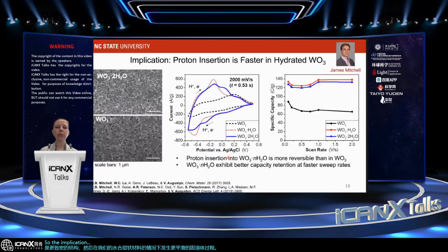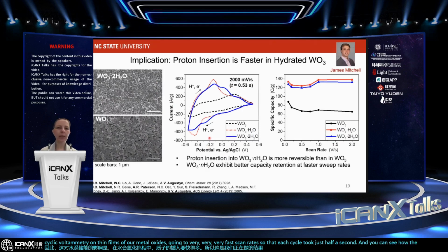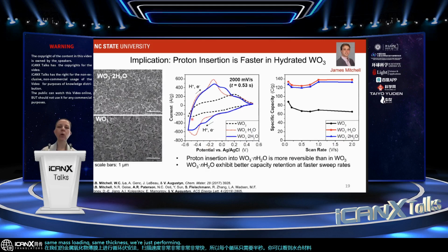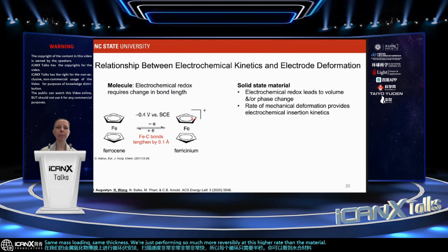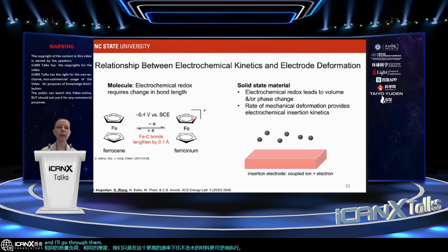So the implication of that for aqueous energy storage is that the proton insertion was much, much faster in the hydrated tungsten oxide phases. So this is a result where we were doing cyclic voltammetry on thin films of our metal oxides, going to very, very fast scan rates so that each cycle took just half a second. And you can see how the hydrated materials, same mass loading, same thickness, we're just performing so much more reversibly at this high rate than the material that did not contain water. And I'll go through this a little bit